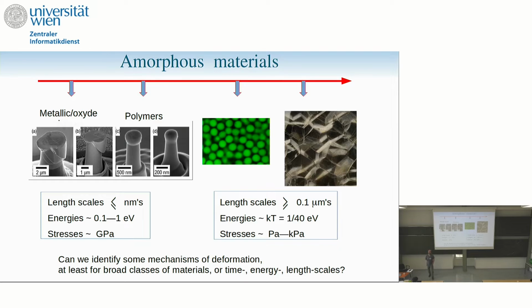Actually, I was a bit surprised. I realized that we never heard about temperature until now. When we start to look at harder systems, like polymers or metallic oxides, oxide glasses, we have much smaller length scales, much larger energies, and associated with these much larger stresses. And temperature starts to matter. Usually in soft condensed matter you work at room temperature and play with density to change the properties of your systems. You have a lot of parameters to change the interactions. With atomic glasses you have much less leeway. You have materials with fixed interactions, and if you want to flow them, you usually have to heat, so temperature starts to play a role.